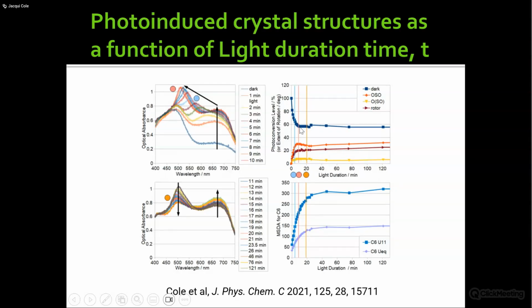Again, you'd expect that. So the SO switching is really quite fast, by the way. And then the oxygen-bound sulfur dioxide has grown really quickly, and is pretty much not quite peaked, but it's certainly peaked here at the pink value. So you're right at the top of this saturation here, right? So that basically seems to correspond with the peak in oxygen-bound sulfur dioxide formation at that point.